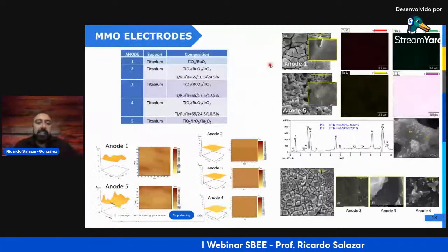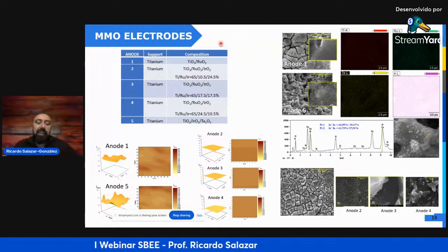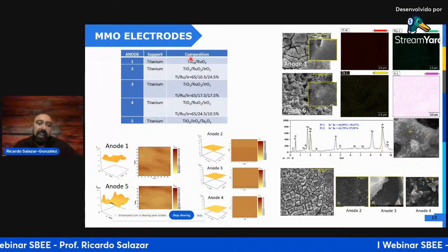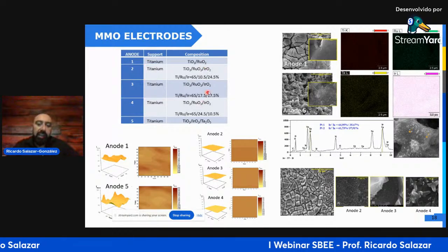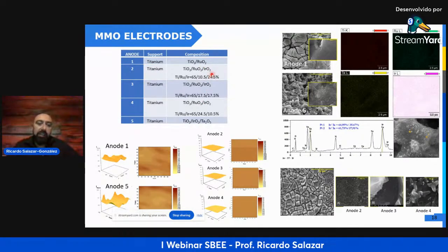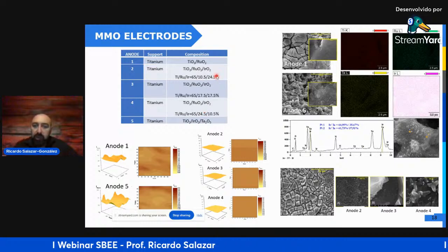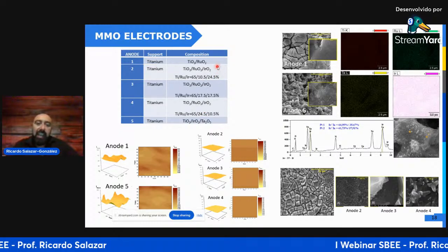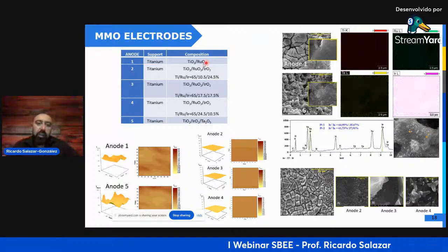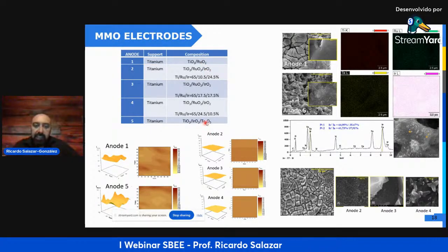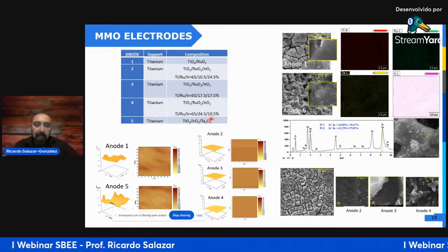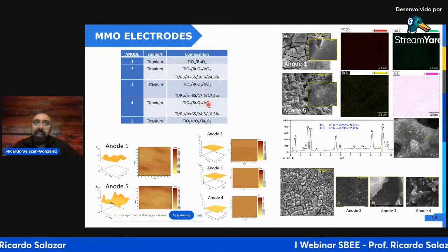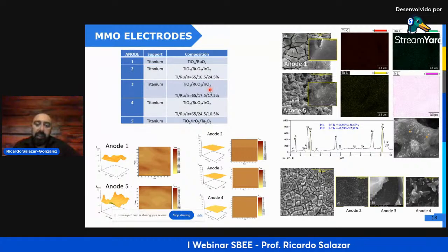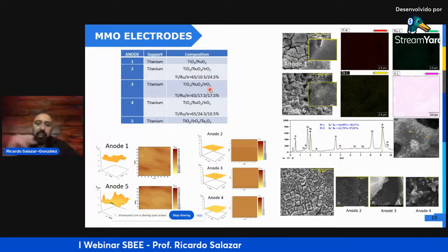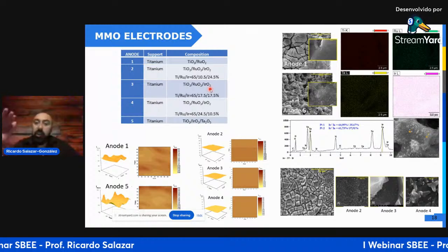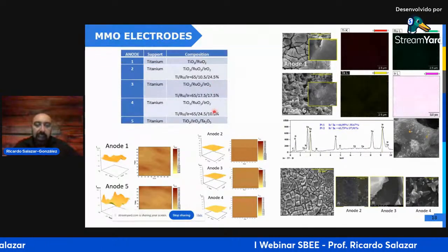On the other hand, in the case of active electrodes, we have the high efficiency of mixed metal oxide electrodes to treat water. This kind of electrode uses, for example, ruthenium oxide, iridium oxide, and tantalum oxide. This kind of oxide are very good catalysts for the chlorine evolution reaction and the oxidation of oxygen on the surface of the electrodes.